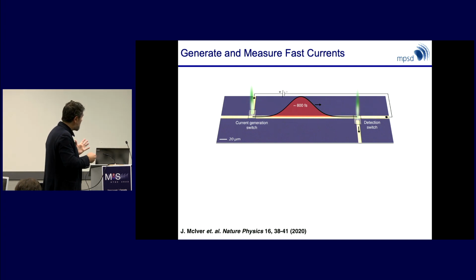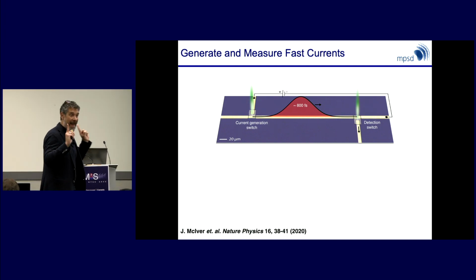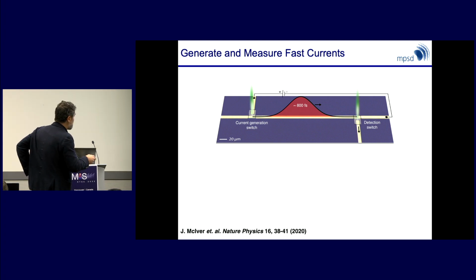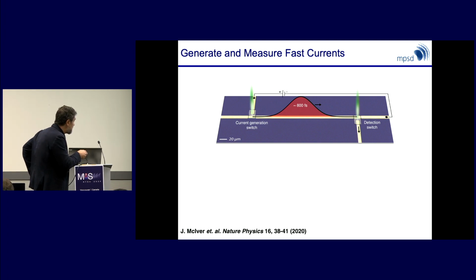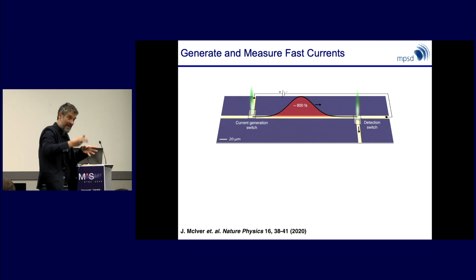Again, the workhorse is one in which we will have at least pairs of switches. You have a switch here and a switch there, and you have a signal line here. You need to design the signal line so that it is not an antenna that radiates into vacuum, but keeps the electromagnetic field confined in the strip line. The first femtosecond pulse launches this current pulse, and then you have a second switch where you detect the effect, where you use the current pulse to bias the photoconductive switch, and you measure this with a femtosecond pulse.